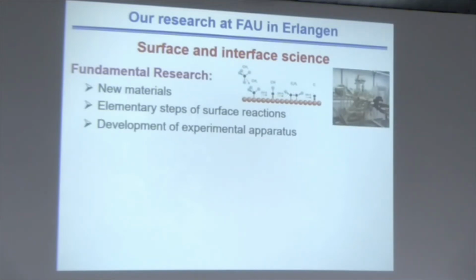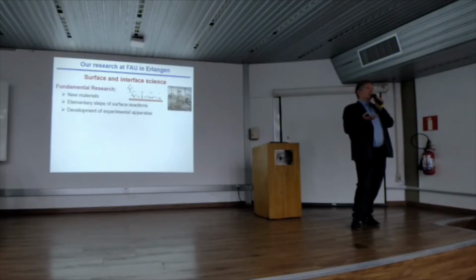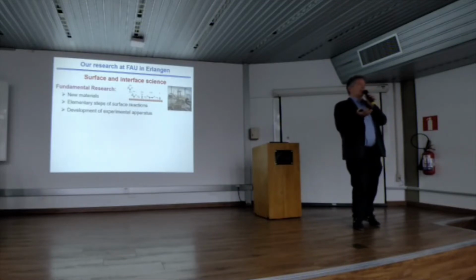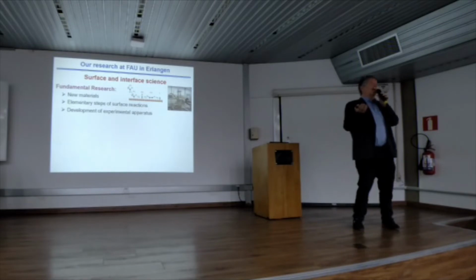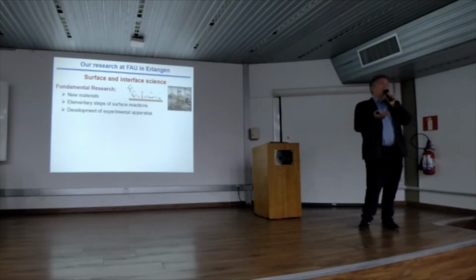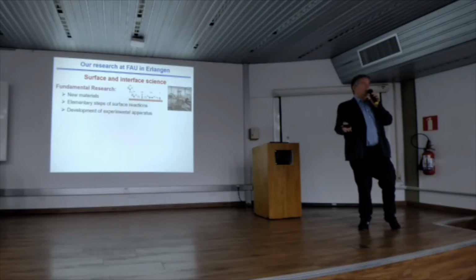And often we are not happy with the experimental equipment that is available. Then we build very specific equipment, typically from commercially available components ourselves. So this here is an XPS machine, for instance, and our idea was we want to do angle resolved XPS on liquids, special liquids that don't have a vapor pressure, like liquid gallium, for instance, or ionic liquids, so you can go into vacuum.